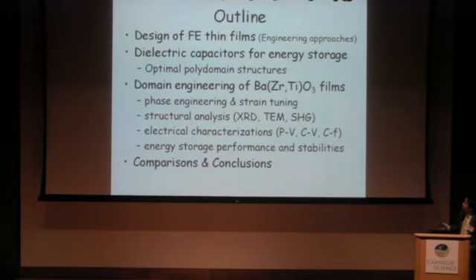First of all, I'm a materials scientist, so I would like to give a general background about how to design ferroelectric thin films. Then talk about high energy density dielectric capacitors, why they're important, and give you a specific way of designing them by utilizing the polydomain structures that are usually formed in epitaxial ferroelectric films. Then I'll give you my example. My model system is barium zirconium titanate, 20% doped in the barium titanate matrix, so 20% zirconium, 80% titanium. And how I achieved a mix of competing polydomain structures by phase engineering and strain tuning. So that's a design point.